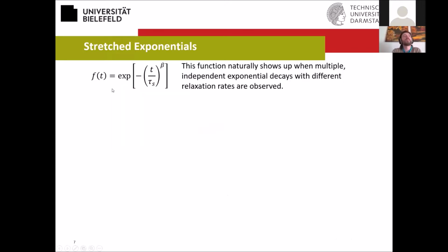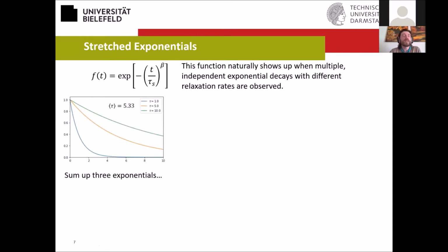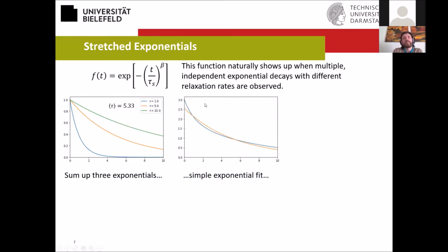Let's do some educational content here. These stretched exponentials basically always show up when you have ensembles of independent exponential decays, where these independent exponential decays have different relaxation rates. Let's have a look at a very simple example. Take 3 different exponentials with 3 different relaxation times, 10, 5, and 1. So the average relaxation time of these is going to be 5.33 and so on. Now you take the sum and try to fit a simple exponential, and you see, okay, this doesn't work because the sum of exponentials isn't an exponential.